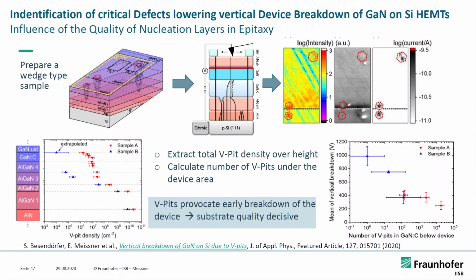And the content of such a V-pit is different compared to the neighborhood. This makes a different electrical property very locally, and this is why you find these leakage spots.